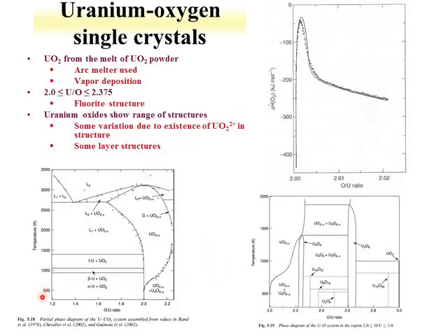We see as we change the oxygen to uranium ratio, here it's below 2 to about 2, a little bit above, we see that we have different species formed, including this one, UO2 minus x, so something that's sub-stoichiometric UO2. And then as we start getting higher in oxygen, we start forming some different species. Here's U4O9 minus y. Here's the higher ratio here. We see that we have U3O8 formed, UO3,